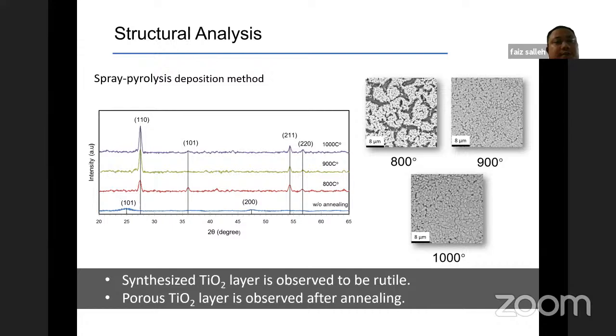And if we are using the spray pyrolysis deposition technique, we can see that after we anneal at high temperature, because by using this method we need to anneal at high temperature to obtain the rutile phase. So we can see here when we anneal it up to 800, 900, 1,000 degrees, the TiO2 layer becomes rutile phase TiO2, but we can also see that when we increase the temperature, we observe porosity inside the TiO2 layer.